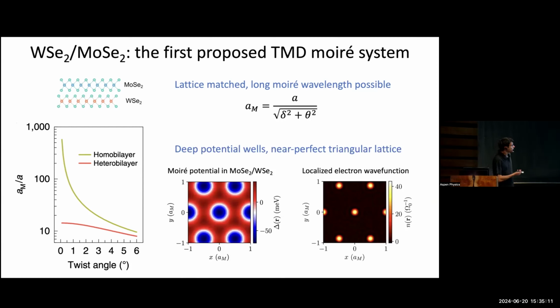The other really nice thing about this hetero bilayer system is that if you calculate the Moiré potential that you realize in it, actually it's quite strong. So you get this nice triangular lattice of minima in the Moiré potential. That's where the carriers like to sit. And because these minima are so deep, of order 100 milli-electron volts, the electron wave functions are very, very localized within these Moiré potential minima.